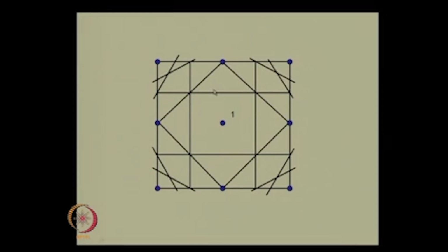If you cross one Bragg plane, but you do not cross a second Bragg plane, then that region is a second Brillouin zone. We find around this point several locations where this is true. So, this is one region where this is true. You have crossed one Bragg plane to get into this region, but you have not crossed further Bragg planes, right, and all these perpendicular bisectors are the Bragg planes by the definition that we have given them. So, we crossed one Bragg plane, we did not cross the second Bragg plane. So, this belongs to the second Brillouin zone, but there is another region here which also belongs to the second Brillouin zone for exactly the same definition, because it fits the same definition. This is another such region and this is another such region. So, taken together we have 4 locations where we identify the second Brillouin zone. So, those are the second Brillouin zone.